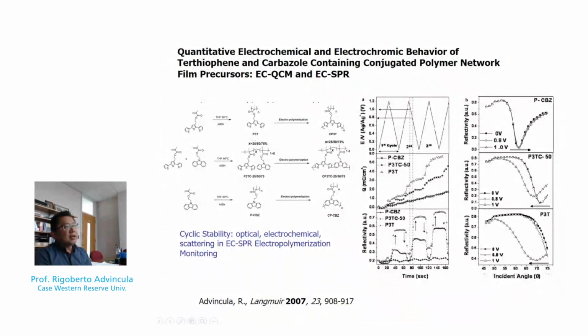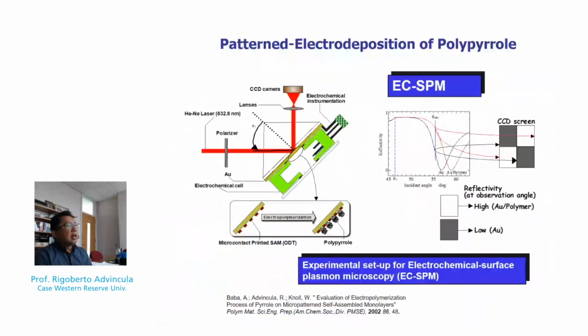So what I can summarize here is different types of polymer and their various oxidized states going to 1 volt tends to shift the thickness and the dielectric property of the deposited film with various thicknesses and copolymers. So in this case, SPR and electrochemistry was done in situ or in real time. Now let me shift to another example. We have here an electrochemical SPR configuration. We then deposited a patterned film on a surface in situ and then ex situ.